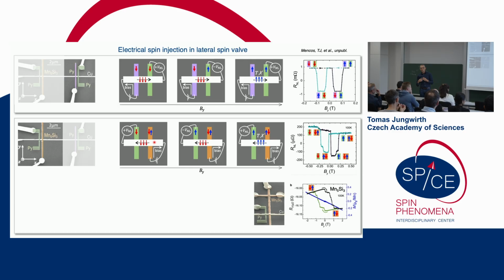Okay? Yes? Another question: if you compare the ferromagnetic and the manganese silicon result, it seems like there's a sort of sloped background on the manganese silicon results on the resistivity. Do you have an explanation of it? There and not with the ferromagnetic. Yeah, so what you also see here is that there is a nice single switching here, while here you have multiple steps in the switching. So this is understood in terms of domains, so that you're gradually switching, you have multiple domains, and you also see it in the anomalous Hall effect. Here you also see some multiple steps, so not complete switching maybe. Okay.